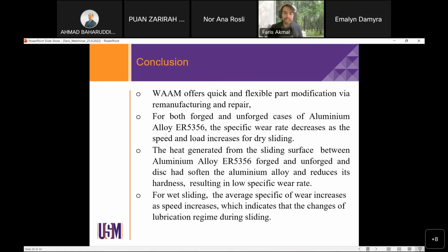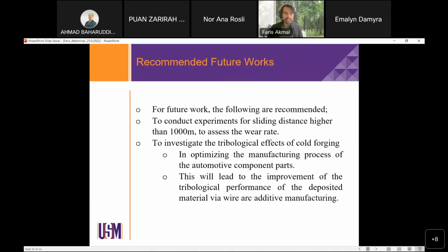Meanwhile, for wet sliding, the average specific wear increases as speed increases, which indicates a change of lubrication regime during sliding. So these are my recommended future works. One is to conduct experiments for sliding distance higher than 1,000 meters to assess the wear rates. Second, to investigate the tribological effect of cold forging in optimizing the manufacturing process of automotive component parts, which leads to improvement of the tribological performance of the material deposited via arc additive manufacturing.